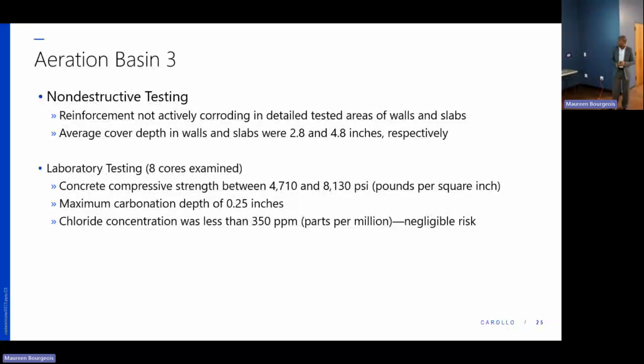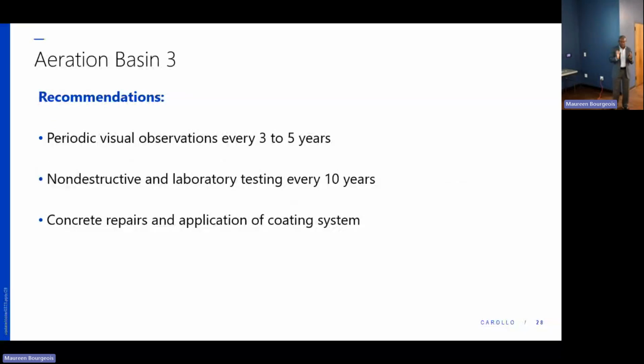So what is our recommendation for the aeration basin? Again, visual observations every 3 to 5 years to take a look at that visually and see how that structure is still performing. Then non-destructive and lab testing, which we talked about, every 10 years. And then we are recommending those areas that are delaminated. We saw the earlier repairs. We said the voids are likely there. We need to concentrate on it. And then also the paste on the surface being eroded there, applying a coating system. We recommend that work to take place in about the next 3 to 5 years.